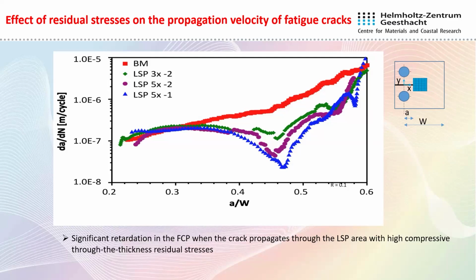You can see the standard samples. The blue square is the area of treatment, and the red line is fatigue crack propagation in the initial case. If you apply different regions of laser shock peening, you can see the slowdown of fatigue crack propagation. It's quite expected, and you have a technique to drive the fatigue crack propagation. Practically, if you have a crack, you can stop it, or you can prevent crack initiation.